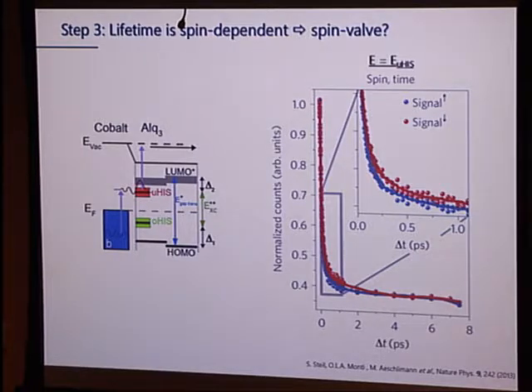But the first thing that you see is that the lifetime is spin-dependent. Spin up and spin down do not have the same lifetime. So that was not quite what we had planned. We thought we would get spin-selective injection. That's not what we saw. But what we ended up seeing was that we have spin-dependent lifetime. So maybe this is still good.